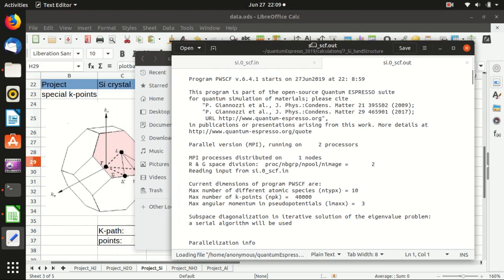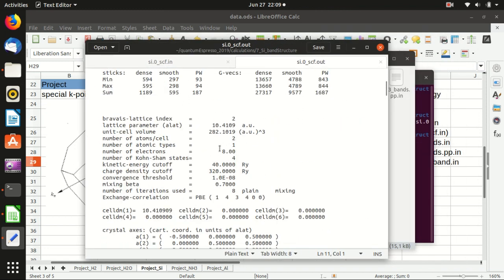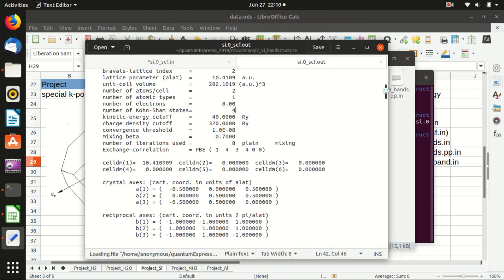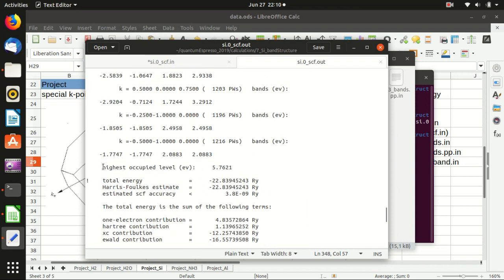If you don't know the number of electrons, you can comment out a line using an exclamation mark and run without specifying the number of bands. In the output file header you can find the number of electrons — there are eight electrons in the system, and it uses half as the number of bands, so four. For an insulator or semiconductor it will be exactly half the number of electrons. However, if you only calculate four bands, those are all valence bands with no conduction band.